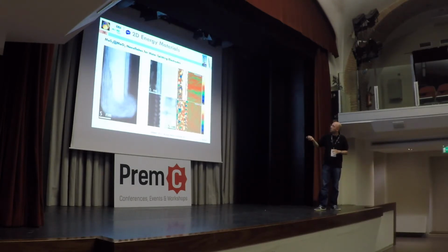So when you go to the atomic scale point of view, you see that the sulfurization is perfect. You have several monolayers here around, and you can see that it's full of misfit dislocations as well. And it's important to know that in this kind of materials, whenever you have defects, there is an increase of the active sites for the catalytic processes. So as far as you have many more of these defects, you are increasing the active sites for the material.